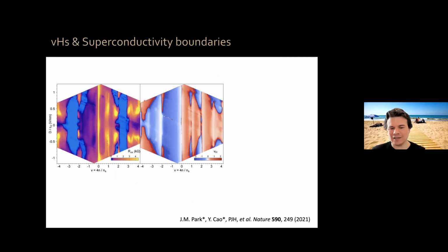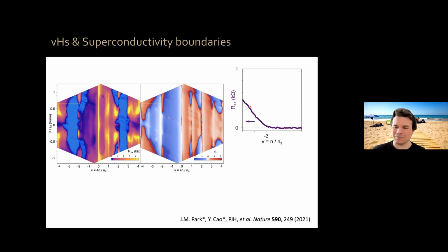So let me show you again this data, and I want to look at what's going on across this van Hove singularity. If I plot the resistivity as a function of filling factor across there, what you can see is that the system is superconducting between -2 and -3, and then at -3 it comes out of the superconducting state. So I can measure the BKT transition critical temperature as a function of filling factor, and of course, it reflects what we know from the resistivity. We have a high BKT critical temperature, and it goes down, and of course, the moment the system comes out of the superconducting state, the critical temperature reaches 0.